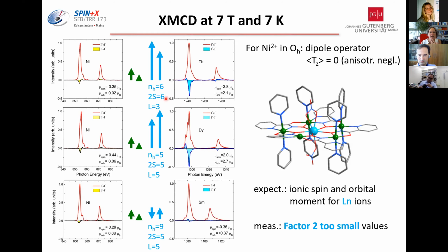overall, the resulting magnetic moment that we should observe should approximately add up to 9 for the terbium, because they are aligned parallel, and 10 for the dysprosium, as they are parallel aligned, but they should be neglecting or annihilating each other because they are anti-parallel oriented for the samarium. And this already gives you an idea why the samarium in this case is not showing a strong magnetic moment. So we did not extensively investigate this further, although we did a little.